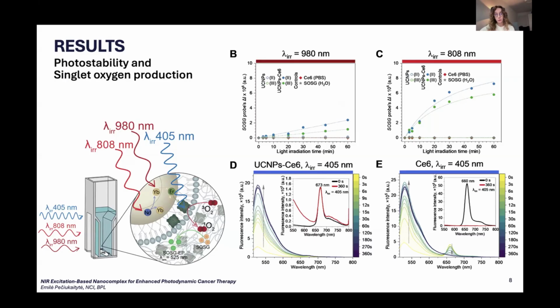PEG density had only minor influence, with the coating containing 33% PEG performing a bit better. Notably, singlet oxygen production under 808 nanometer irradiation was more than 3 times higher compared to 980 nanometer laser excitation. Additionally, a very important part is that chlorin e6 within the nanocomplex showed minimal to no photobleaching, whereas free chlorin e6 was rapidly bleached out under the same radiation conditions, which shows chlorin e6 stabilization and that we could use this nanocomplex repeatedly.